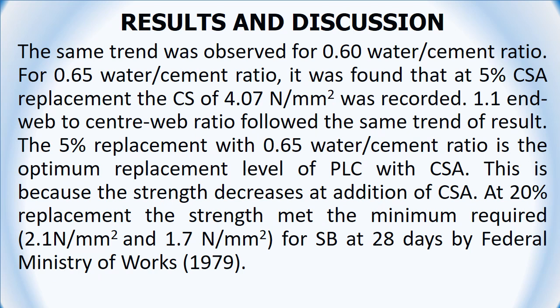The same trend of result was observed for 0.6 water cement ratio. For 0.65 water cement ratio, it was found that at 5% CSA replacement, a compressive strength of 4.07 Newton per millimeter squared was recorded. The 1:1 end-web to centre-web ratio followed the same trend of result. 5% replacement with 0.65 water cement ratio is the optimum replacement level of Portland limestone cement with coconut shell ash.